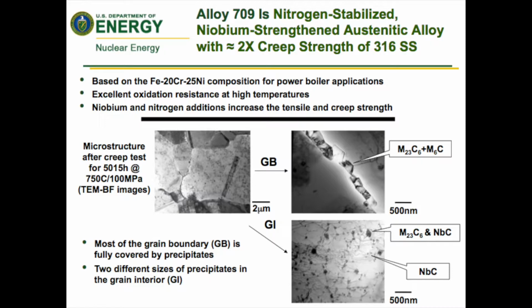709 is based on the 20 chrome 25 nickel composition. It was originally developed for power boiler applications. It has excellent oxidation resistance at the kind of temperatures that we are looking for. And you can see, if you look at the variety of microstructures that are shown, these are post-creep microstructures after 5,000 hours at 750 C.